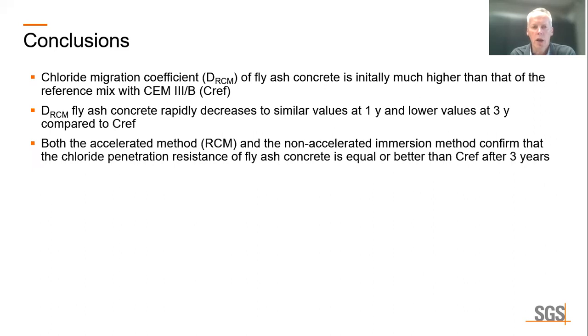That both the accelerated method and the non-accelerated immersion methods confirm that the chloride penetration resistance of fly ash concrete is equal or better than the reference concrete mix after 3 years.